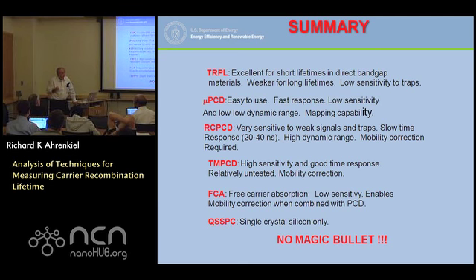If it's direct radiative recombination, the lifetime actually decreases as you lower the temperature, because the B coefficient, the radiative coefficient, becomes stronger. So the lifetime will shorten as you cool. So these are all parameters that one can address if the situation requires working that hard. So there's no magic bullet. You do a number of experiments, and out of those you hope to get enough information to figure out what's going on inside this material. But it's not always easy.